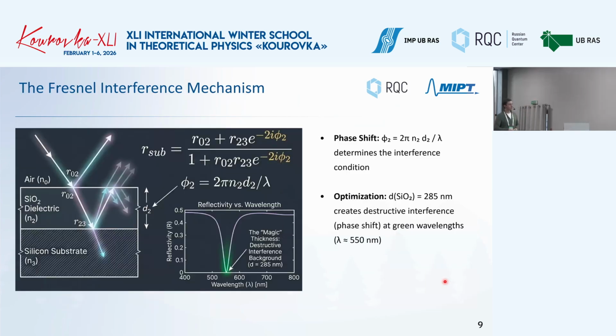Okay, moving further. So how is it happening exactly? So you have the Fresnel interference mechanism, and you can calculate it like with this formula. There is a phase shift that depends on the N2 value of the dielectric, and then the width of this dielectric, of this oxide. So you can basically purchase this substrate with different values of the thickness of this SiO2, and this determines the interference condition. So it turned out that for some specific thickness, let's say 285, it's very easy to see the reflectivity around 550, where our eye is very sensitive to the changes.